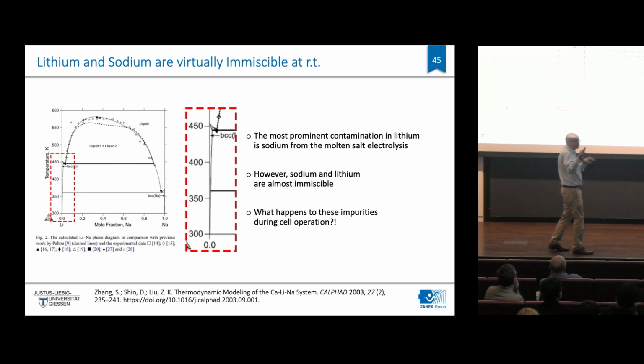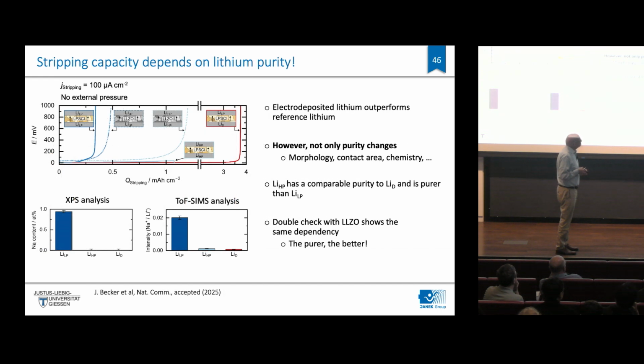That means there are sodium particles in your lithium, and very little sodium is really dissolved in the lithium. Depending on your supplier, you have different qualities of lithium. And we found, by the way, that this is really critical, because if you take different qualities of lithium and strip it, the impurities, of course, don't dissolve in the solid electrolyte. Solid electrolytes are highly specific for the mobility of one charge carrier. The sodium simply does not enter into the solid electrolyte, so it remains at the interface and increases the resistance